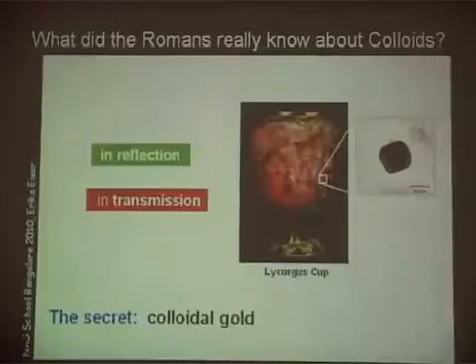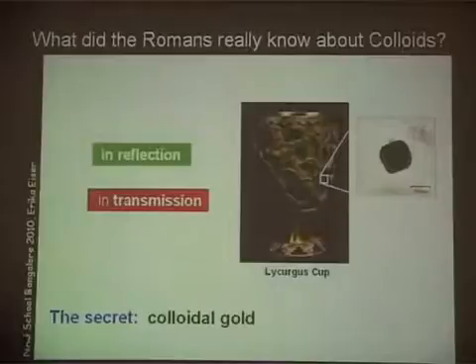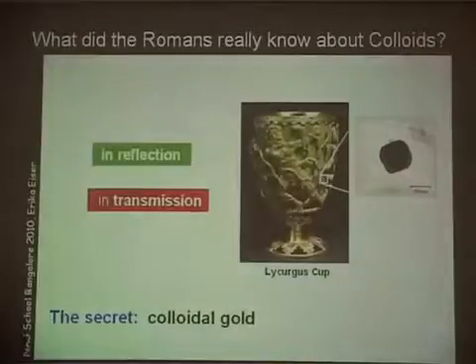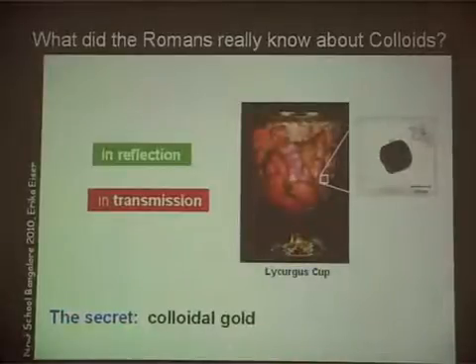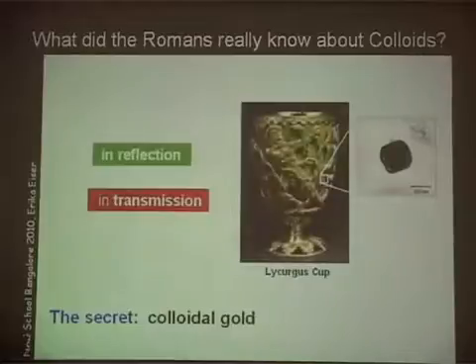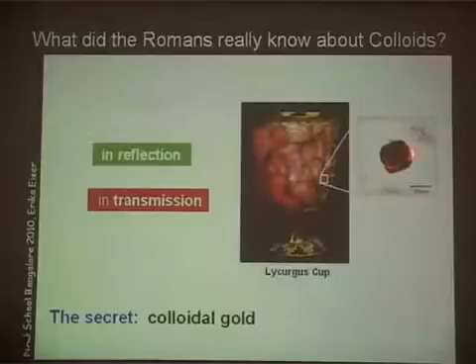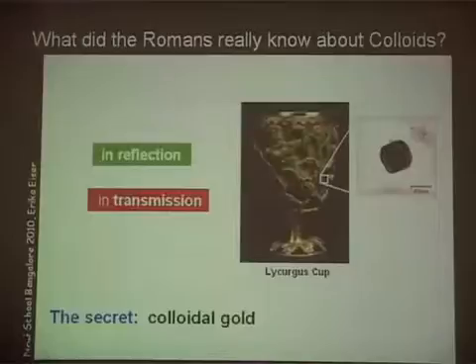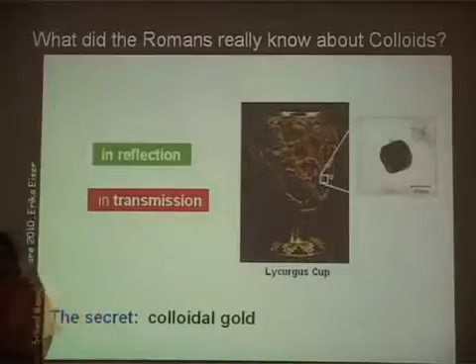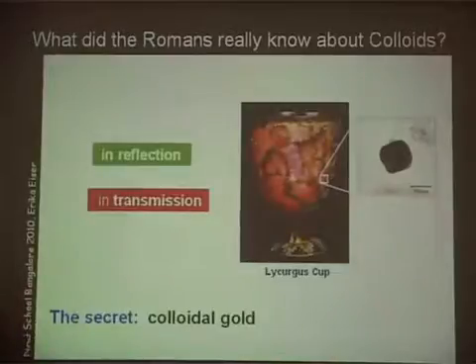The secret the Romans knew about, that you had to do something, but they couldn't really figure out or control, is to use colloidal gold. Some analysis made maybe 10 or 20 years ago showed that indeed there are some small silver and gold colloids of about 50 nanometers in the glass. A very minute fraction, but it is sufficient to color the glass.